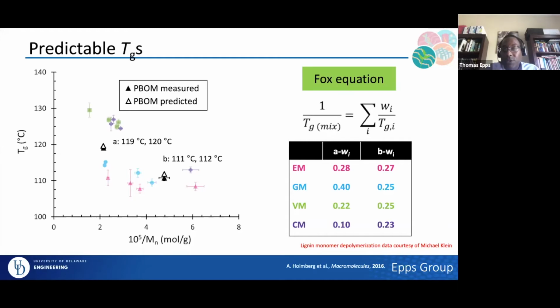Then what we are able to do is we're actually able to use the Fox equation, shown in the top right of the screen, to predict what the glass transition temperature of a mixture of those components would be if we polymerized it based on the homopolymer data that we'd gotten previously.